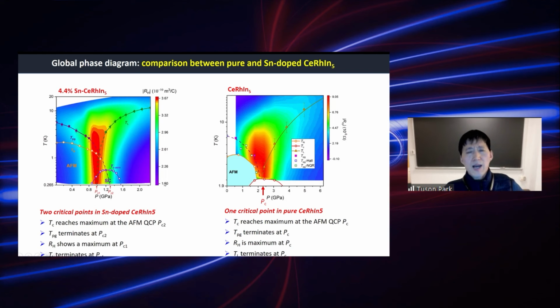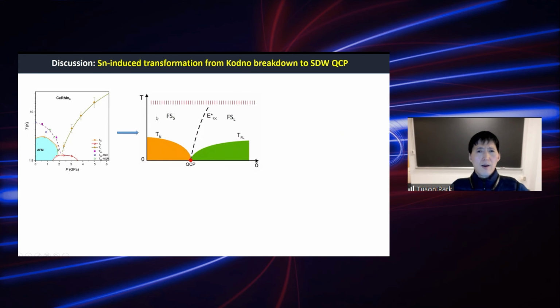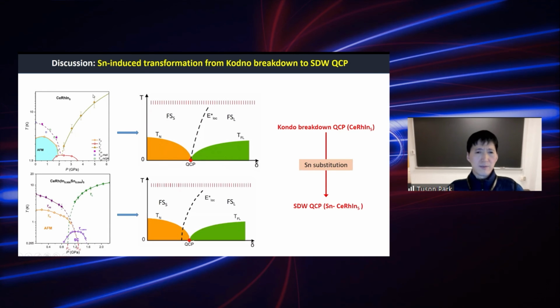So how to understand this new temperature scale T sub L and the new critical point PC1 in the tin compound? So according to the Kondo breakdown type scenario, this quantum destruction or charge delocalization point should end at this point. So we can think that this point actually represents this charge delocalization point. Also in the tin compound, this is a SDW critical point where the moments are localized, within the antiferromagnetic phase, which is what happens here, leading to an anomaly in the Hall effect and the resistivity.